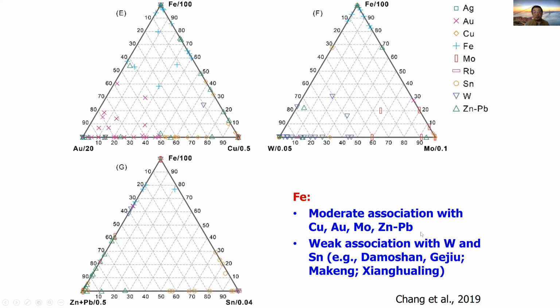So we can have lots of magnetite in skarns. In copper skarns, a lot of them, volumetrically, you look at them, there's much more magnetite than sulfide. And so the lesson here is not to confuse this with IOCG deposit. Some people just look at it, oh, there's magnetite and copper or gold, so it must be IOCG. So not necessarily. You have to look at the geology rather than just look at the metal.